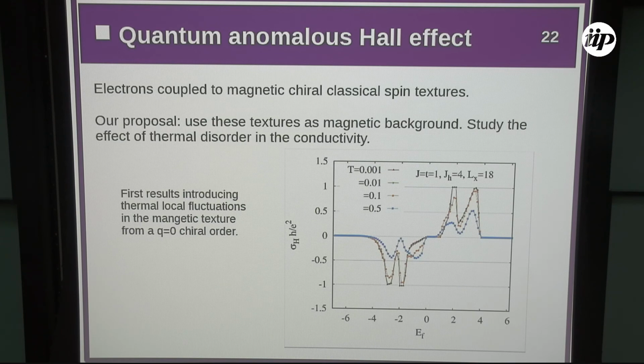But in this particular plot I'm showing, we took one of these Q equals zero orders with chirality, and we put some thermal fluctuation. We are working with Monte Carlo, but what we do here to just get a feel of what happens with temperature is a local fluctuation in each of the spins, okay? What you can clearly see is that at very low temperatures, the conductivity is quantized, but of course, as you go up with temperature, the features start to erase, okay? And this is for a Q equals zero order. For example, the associated Hamiltonian is this kagome with a Dzyaloshinskii-Moriya.